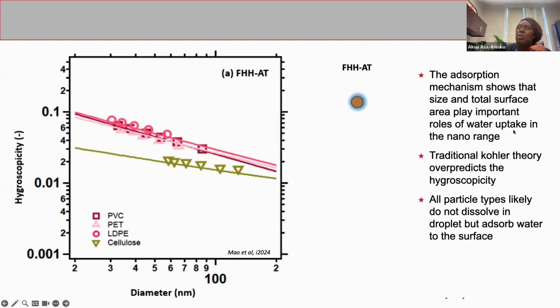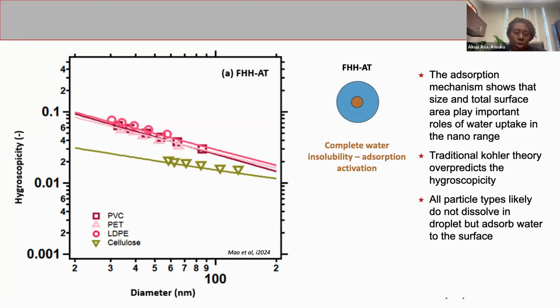So let's see how it applies to our nanoplastics. When we look at the hygroscopicity as a function of diameter, now applying FHH, which is the adsorption theory, we see really good agreement for our nanoplastics and also for cellulose as well. In this case, the adsorption mechanism implies that the size and the total surface area play an important part in the water uptake. And it agrees well with not just the data, but the model actually agrees well with the data, I should say. So again, all particle types do not dissolve in the droplet.